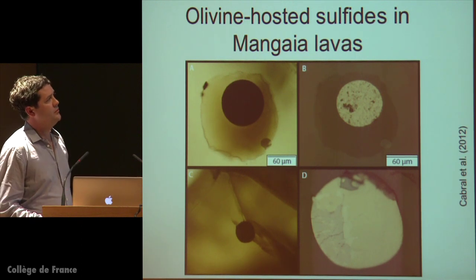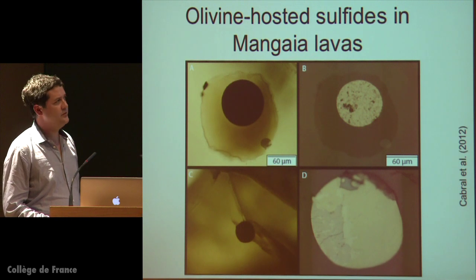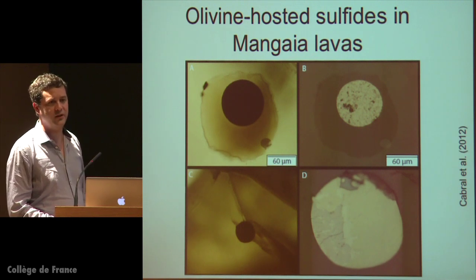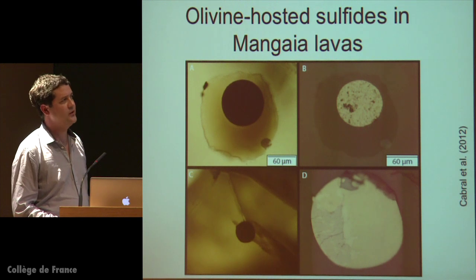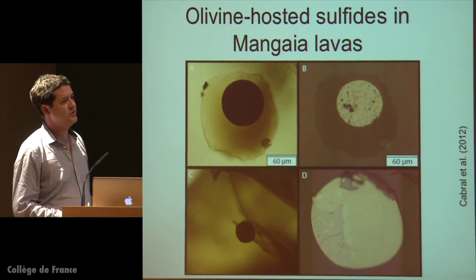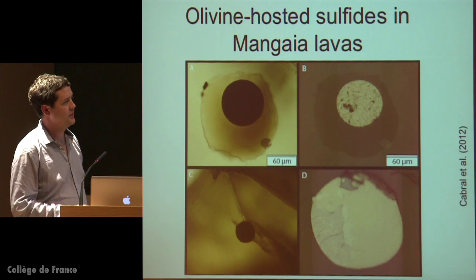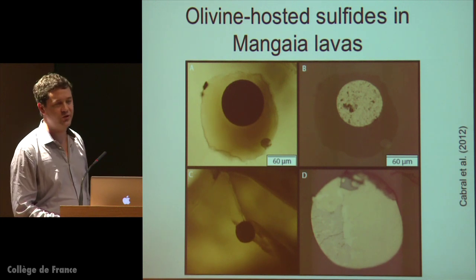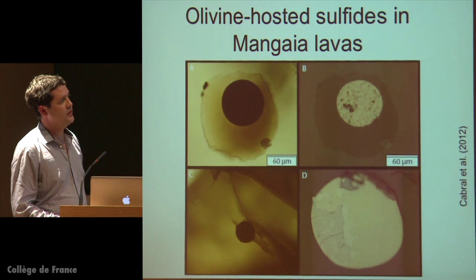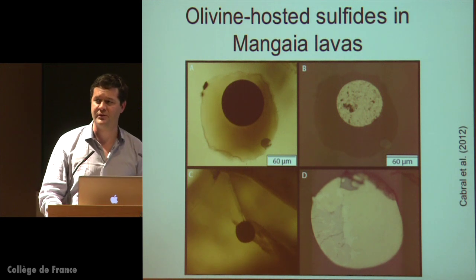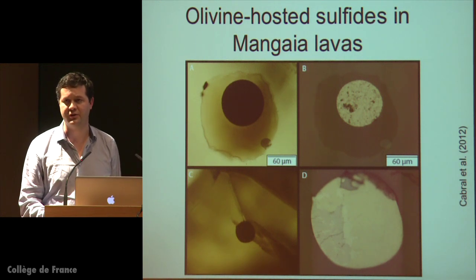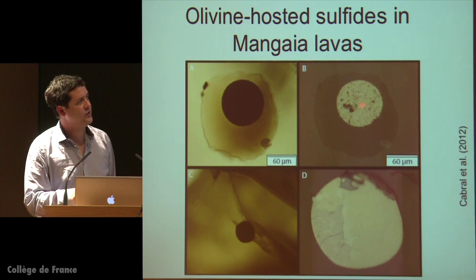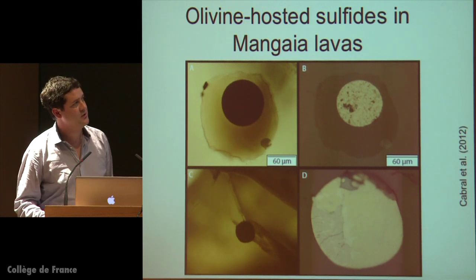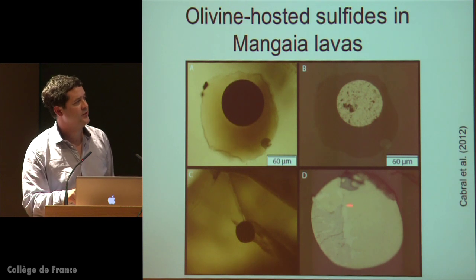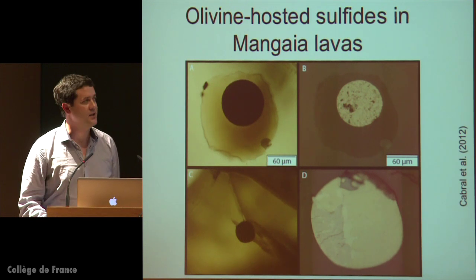So my student crushed around 5 kilograms of material and pulled out olivines from all of this material and looked at each olivine under a binocular microscope and exposed the biggest inclusions. And over the course of about 3 months, she found hundreds of sulfides, but they were all tiny, too small really to do much with. But she found 2 large sulfides. Here's one that's maybe 80 microns, 100 microns. This one is well over 100 microns.